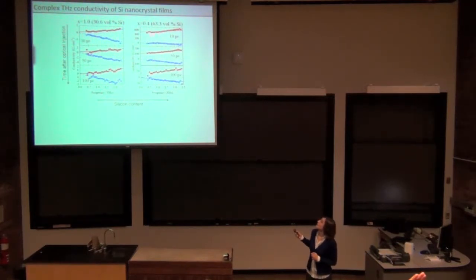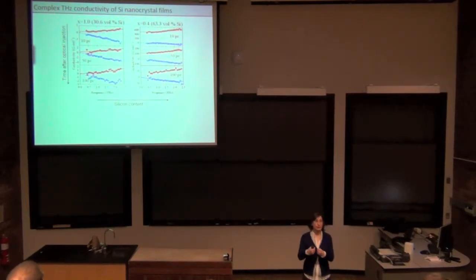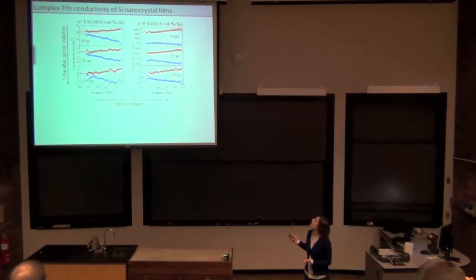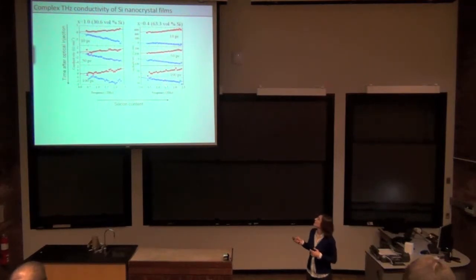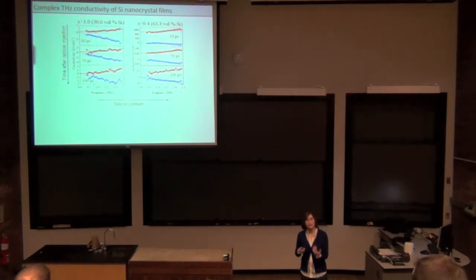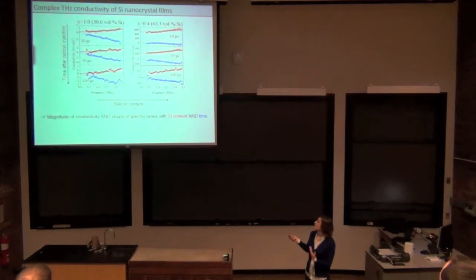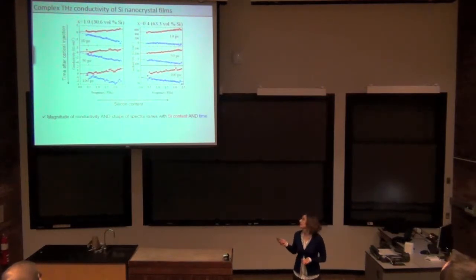First of all, looking at the different compositions at early times, the spectra are very different. Here, where we remember from TEM the nanocrystals are far away from each other, you see very strong localization, very strong suppression of the real conductivity, while in the other one you have quite high real conductivity. The other thing, if you look along the time axis, is that it starts out with high conductivity, and as time goes on, close to 100 picoseconds, this starts looking almost like this. So we are somehow seeing changes in the degree of localization of carriers, in the shape and in the magnitude of conductivity.